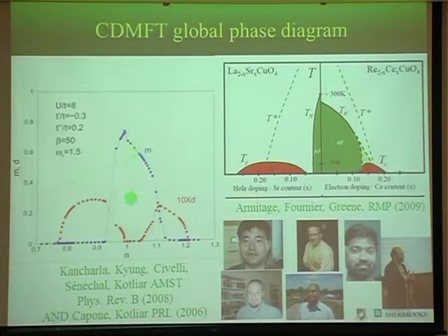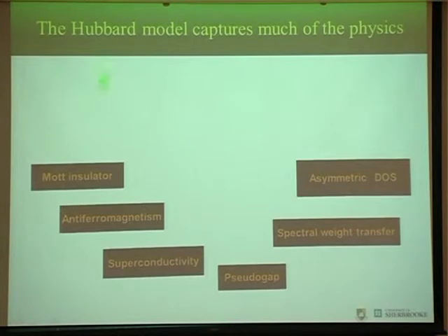in blue here at 0 temperature, you see this asymmetry that is shown in the phase diagram. It is larger on the electron doped than on the hole doped side. There is some coexistence here that is seen. The width of the phase is larger on the hole than on the electron doped side. But on the hole doped side, we have problems because there's too much coexistence, and in fact, the charge density wave phase is not there.